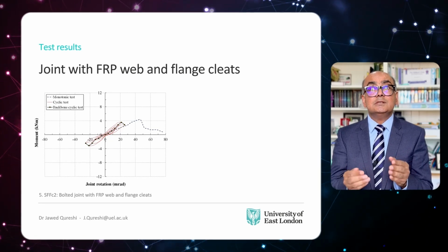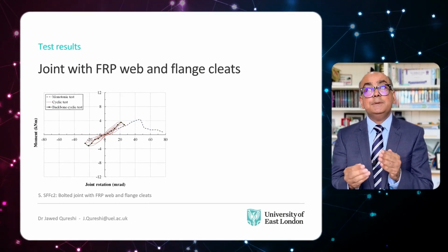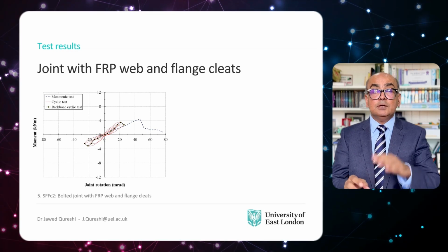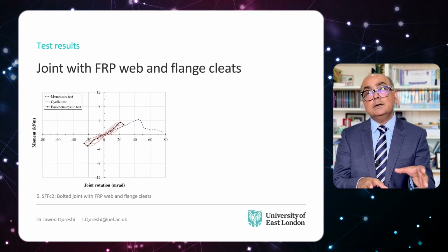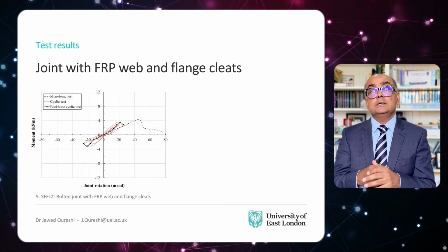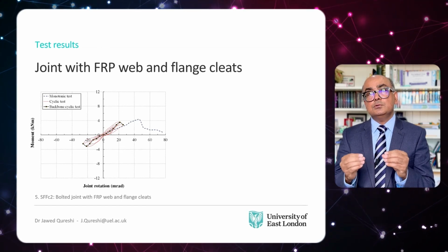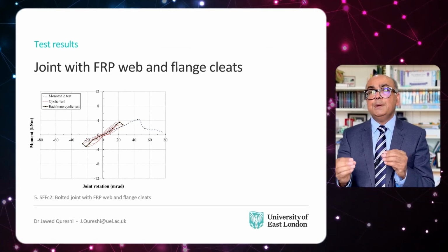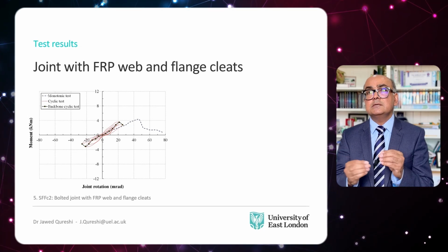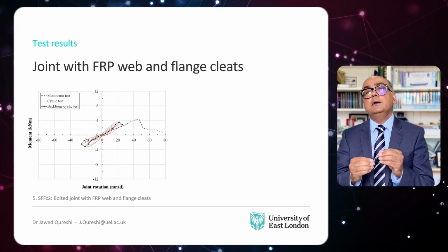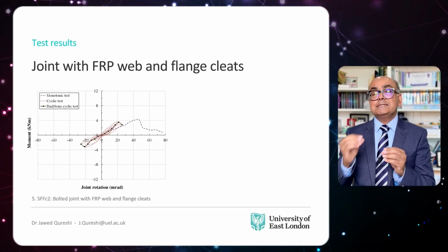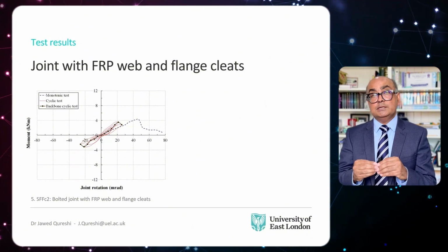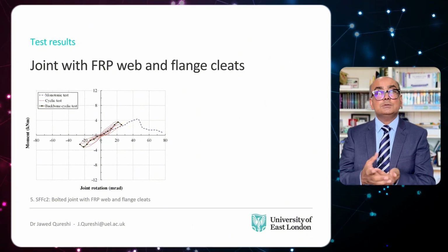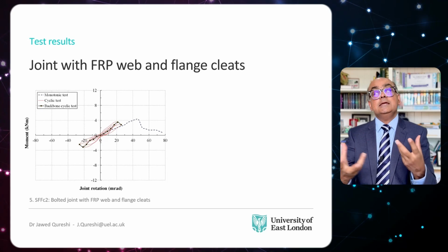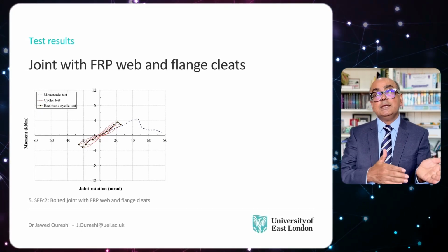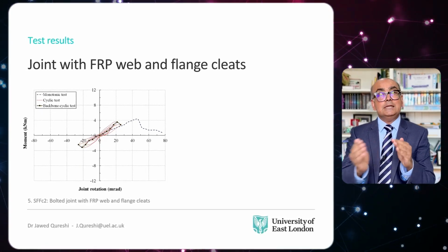These are test results for joints with FRP, web and flange cleats. Other 4 tests that I mentioned earlier, they used steel cleats. It is important to note here that both moment and stiffness is far lower as compared to steel cleated joints, which is quite obvious because when we use FRP cleats, the failure can be due to delamination and cracking, which I talk about little later.